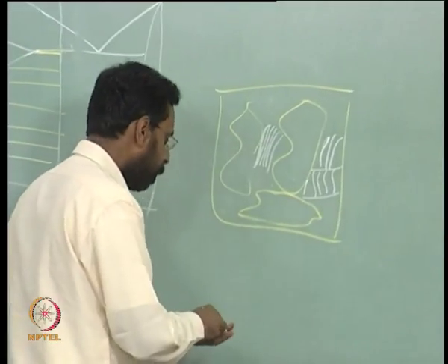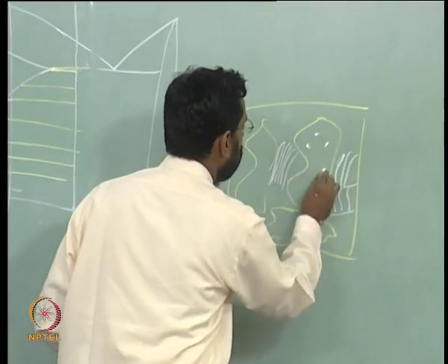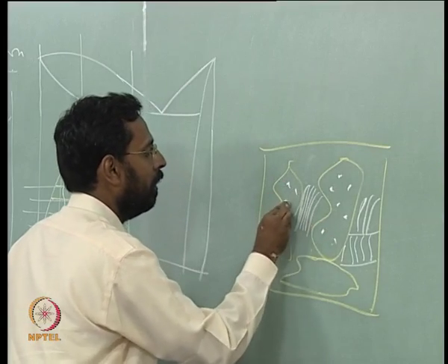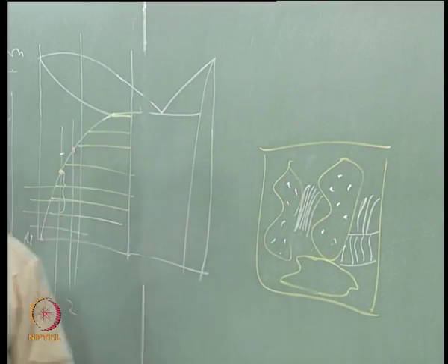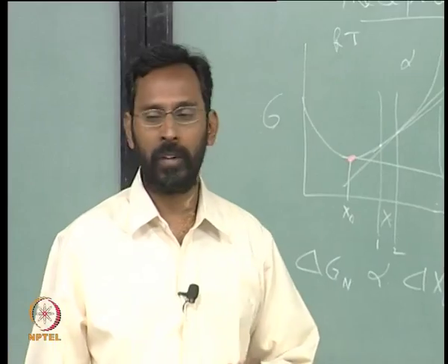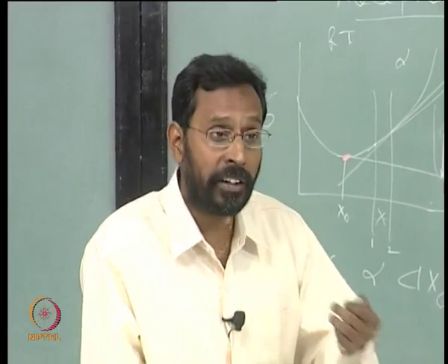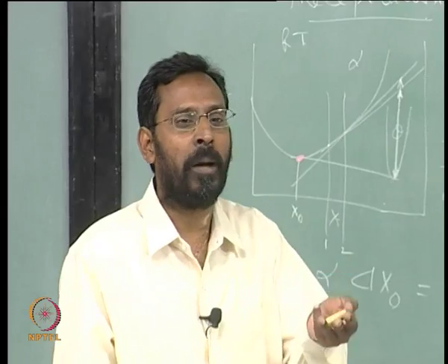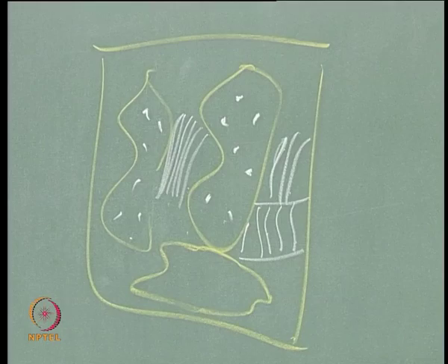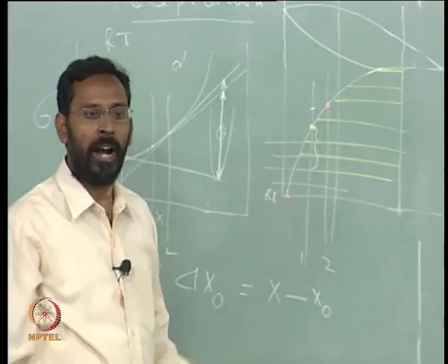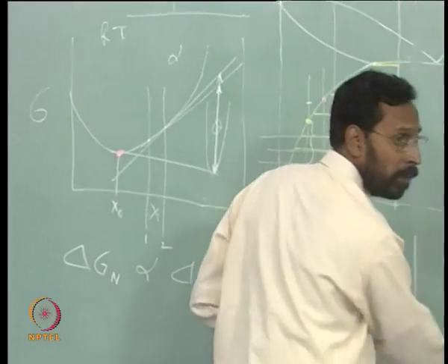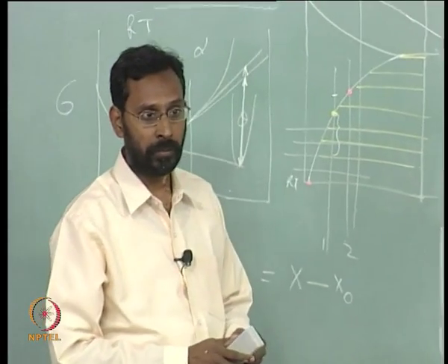particular alpha precipitates inside it some phase, depending on the undercooling that we are talking about. In the last class we talked about whether GP zones come out, or theta double prime, or theta prime, or theta comes out. It depends on the temperature at which we are doing the age hardening for a given alloy. That is what you have seen, the different solvus lines we have drawn. But when theta is already there, why does it have to nucleate inside the grain?